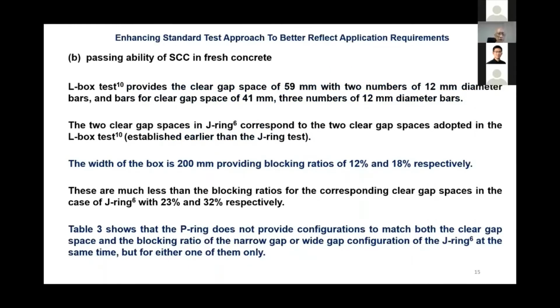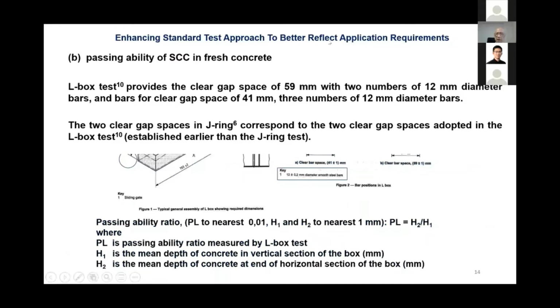Now, the width of the box is only 200, ended up with a blocking ratio of 12% and 18% of the cross-section, against more like 23 and 32 in the J ring. So we do not think that the two tests are actually directly linkable. So they are separate tests having separate interpretation. I wonder what happens if he passes one and fails the other. The engineers have a big headache trying to decide which one to say is the controlling test.